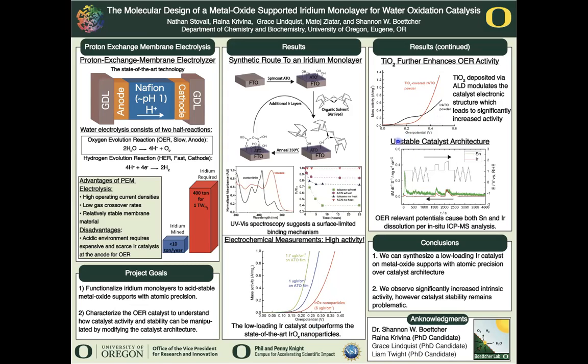But it's still not that stable, is what we learned. Looking at this trace here on top, this is just showing the potential we're applying within our electrochemical cell related to the axis here on the right. And down here, we have this noisy tin signal, and then your iridium signal related to this axis on the right. And essentially what we see is as we increase the potential up into what I'll call OER relevant regions, we see spikes in these bottom traces here. And what that means is that we're actually losing catalyst on the surface of our electrode. It's falling off or it's dissolving.